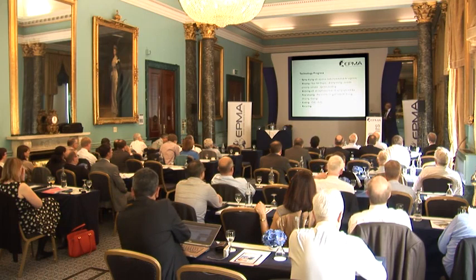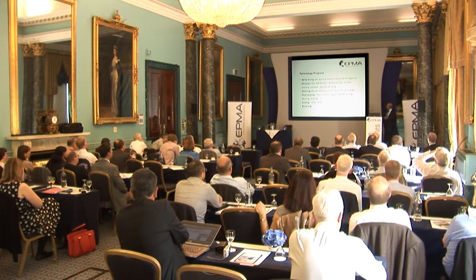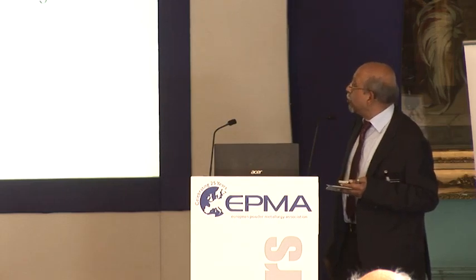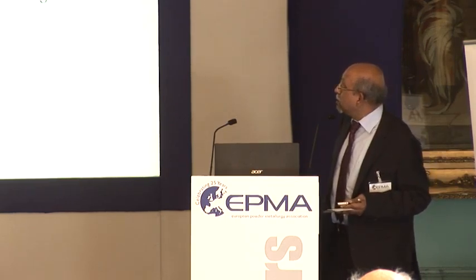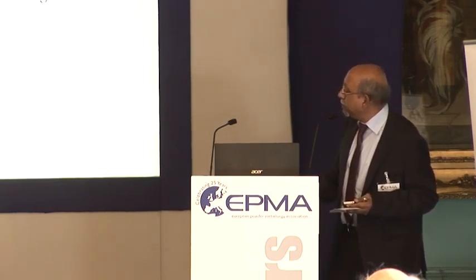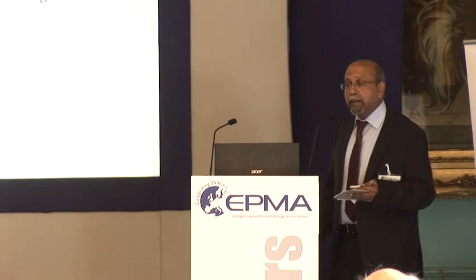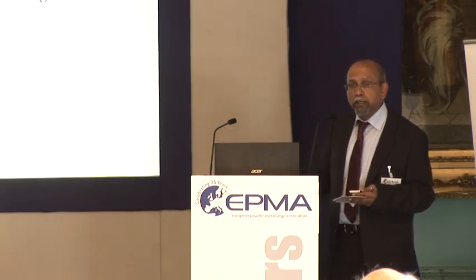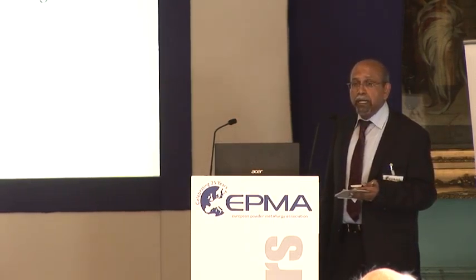A few words about process equipment. What has happened in the last 25 years, we have seen the onset of spray drying with water instead of organics. We are getting closer to near net shape due to direct pressing, due to the accuracy of the dies as well as the machines. We go to isostatic pressing, extrusion, injection molding. In sintering, the advances are sintering with atmosphere control. That means we can change the atmosphere and control the carbon content at different stages depending on what's going on during the process. And using sinterhip as a post-consolidation treatment to get rid of all the remaining pores that are still open.